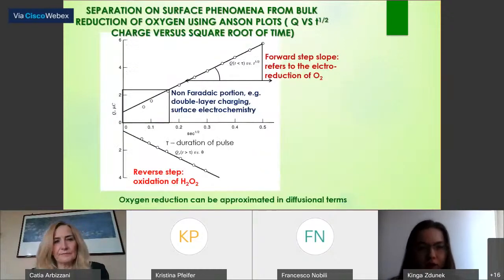This slide presents separation of surface phenomena from bulk reduction of oxygen using Anson plots. At the beginning of the process, we observe a non-Faradaic portion, for example double layer charging or surface processes. We can see that the curve is not linear. After that we observe a linear dependence, and it is the reduction of oxygen, and the reverse step is oxidation of hydrogen peroxide.